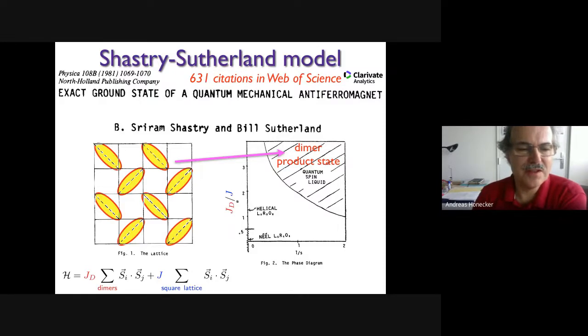Now, what is the point here? The point is if you put strong dimers on the diagonal, you get an exact ground state, which is a product of dimer singlets. And it's not only an exact eigenstate, in fact, for the strong dimer coupling, it's the exact ground state of this model. In the original paper, they also had a kind of phase diagram where the vertical axis is the ratio of the coupling in the dimers and the square lattice couplings. The horizontal axis is the inverse of the spin value, so the extreme quantum limit spin 1/2 is on the right side. And you see that for the strong quantum case and strong dimer coupling, you get this dimer product state.